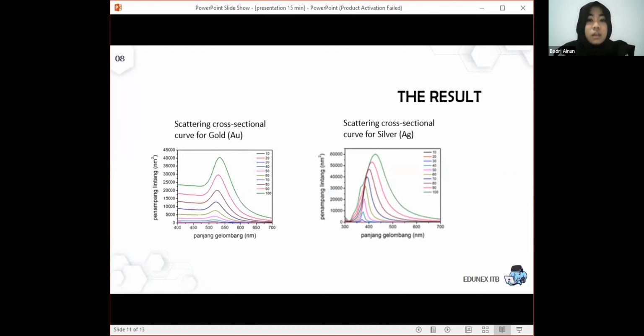And here are the results. We have the scattering cross-section curve for gold on the left and for silver on the right. You can see the difference in the range and peak for each curve. The variation of radius is from 10 nanometers to 100 nanometers. For the gold material, the peak of the curve for a radius of 100 nanometers is only about 40,000 nanometer square. And for the silver material, the peak of the curve for 100 nanometers is about 60,000 nanometer square, and the range of the curve for gold is wider than the curve for silver.